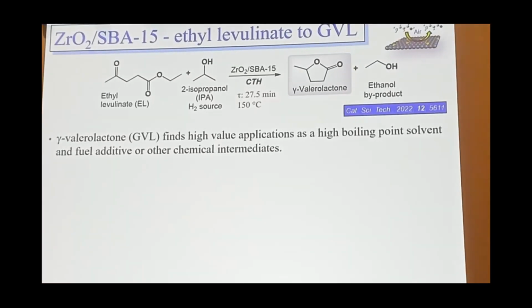These zirconia samples can also be used for other cascade reactions, now taking advantage of the Lewis acidity of these materials. Just at the moment in cascade catalytic transfer hydrogenation, in which you use isopropanol as your hydrogen source. Now, in this case, the process advantage really comes from the fact that you don't have to have the hazard associated with using gaseous hydrogen. But zirconia is very effective at this transformation, essentially taking ethyl levulinate, again you can derive from sugars, and turning this into gamma-valerolactone.